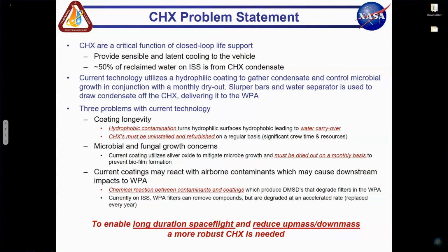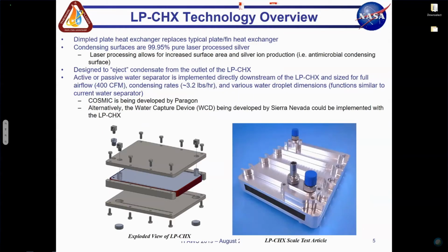The current coating uses some silver oxide to mitigate microbial growth. It also has to be dried out on a monthly basis, and we want a heat exchanger where we never have to dry it out again to prevent that biofilm from forming. And then the third one is that the current coating reacts with airborne contaminants, which produce potentially harmful substances that degrade the filters in the WPA, which is the water processor assembly. So we're really looking at this technology to enable long duration space flight and reduce up mass and down mass. And really our goal is to create a more robust condensing heat exchanger.